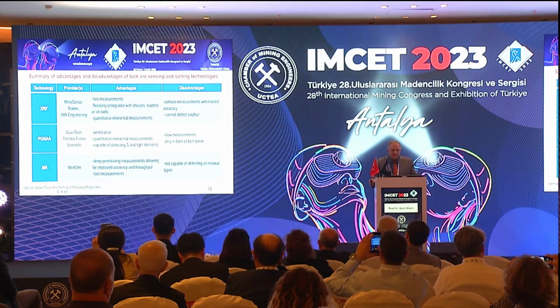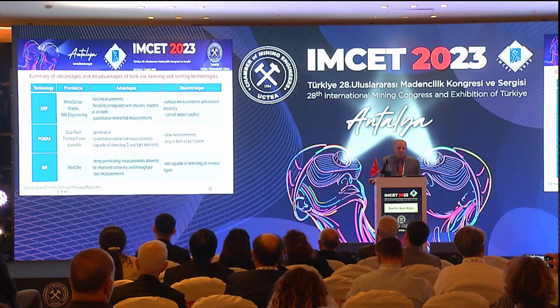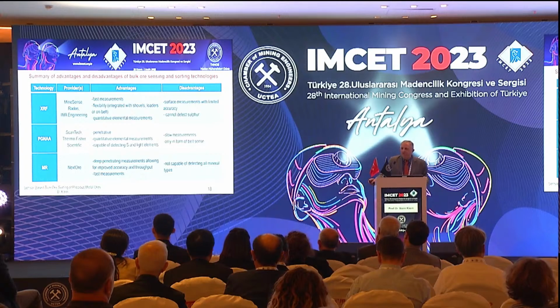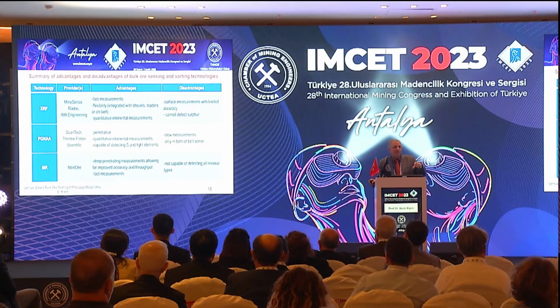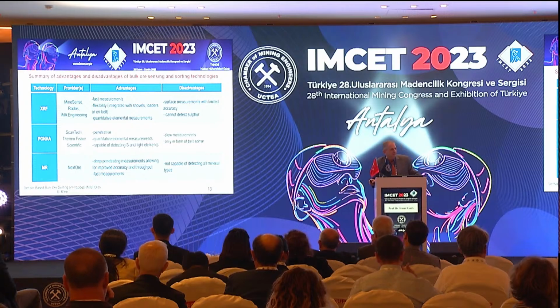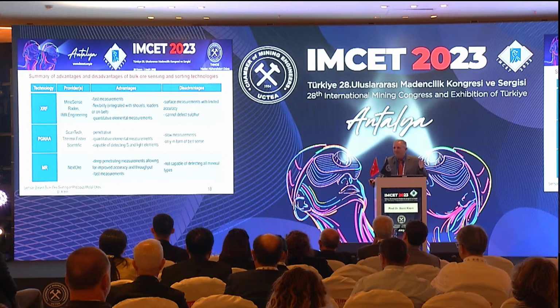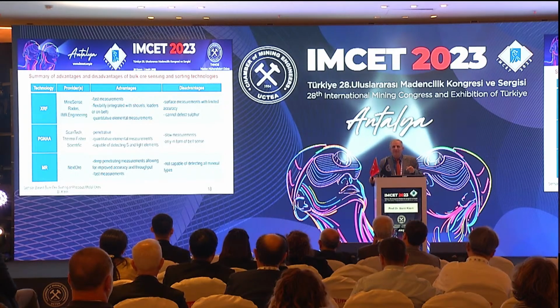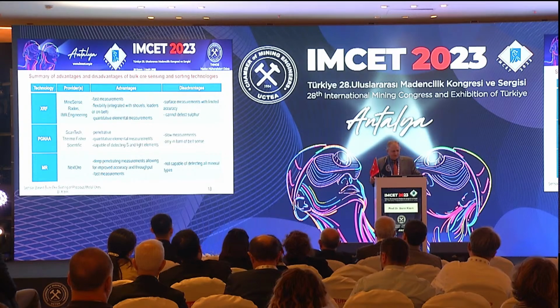The XRF is fast. You can put it on shovels, conveyors, and it gives a quantitative elemental measurement of certain elements but not precious metals. Disadvantages, it's only actually measuring what's on the surface, so what's on the surface has to represent what's in the rock as well, and it cannot detect sulfur for bulk ore sorting. A laboratory analytical XRF can detect sulfur, but not when you have it a meter away from the material that you're trying to sense. There's too much interference from moisture and other factors.